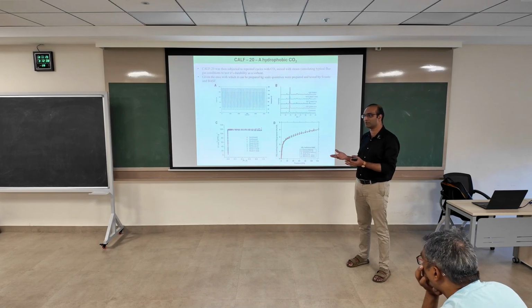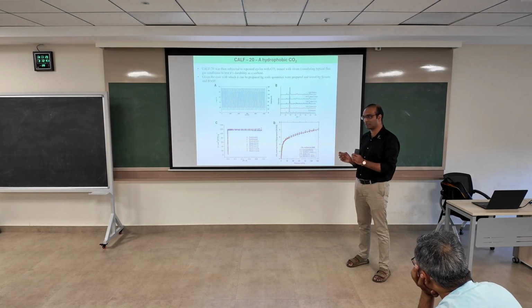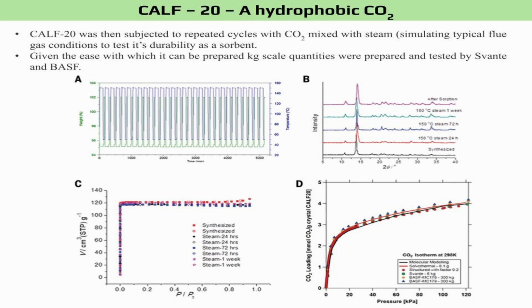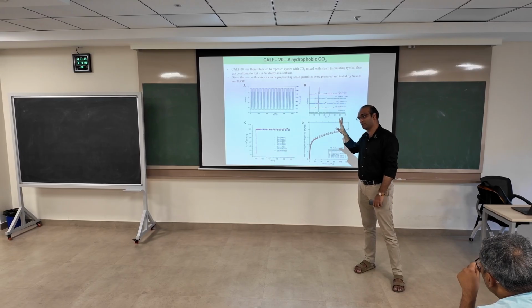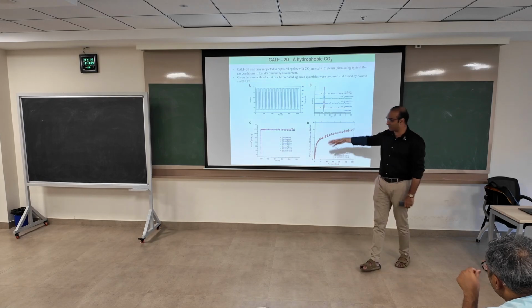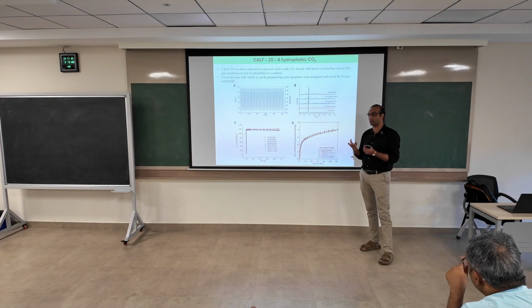It's not, like it's just solution. You can just mix the chemicals in water. The only problem is that you might have to use some solvent like DMF, dimethylformamide. But then you can always reuse that solvent. Once you make the MOF, it usually precipitates out. It's a solid powder which can be easily separated from the solvent, and you can recycle the solvent. And the temperatures that they use are like 100 degrees Celsius, even if you scale it up. So in that sense, it's better than making most of your liquid adsorbents, which are actually very energy intensive.